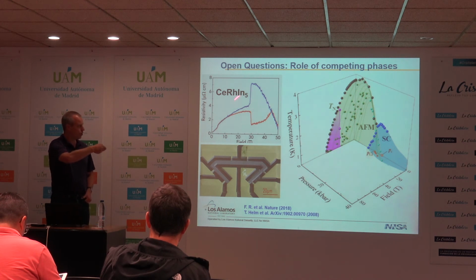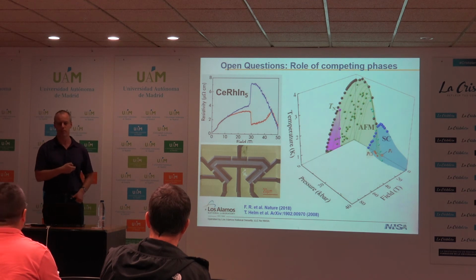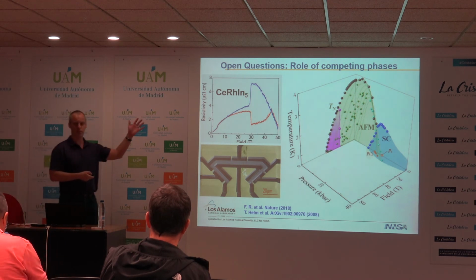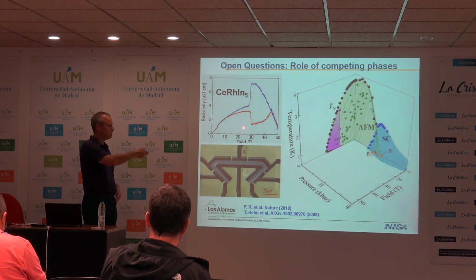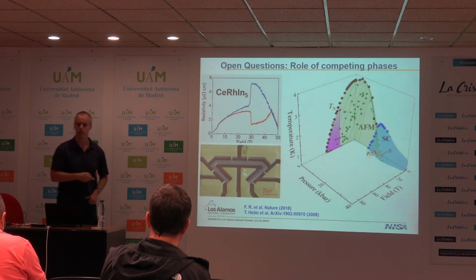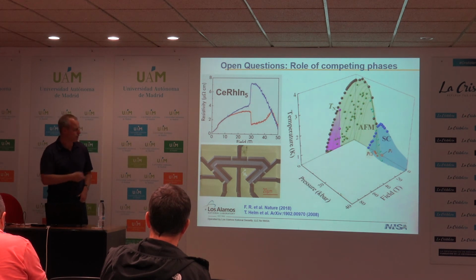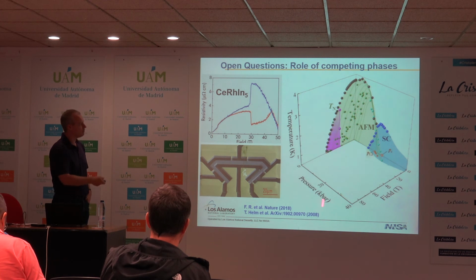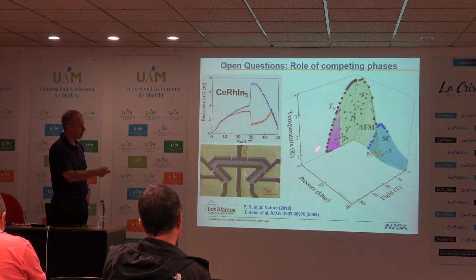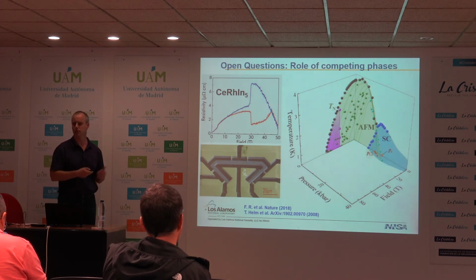And so all signs point to this being something happening in the electronic degrees of freedom. In fact, the only other signature that we have is that the quantum oscillations change as you go through this 30 Tesla transition. So some form of order. And so now when you look at the temperature, pressure, magnetic field phase diagram, here we have magnetism and a dome of superconductivity, and now here we have some form of nematic-like response in this system.